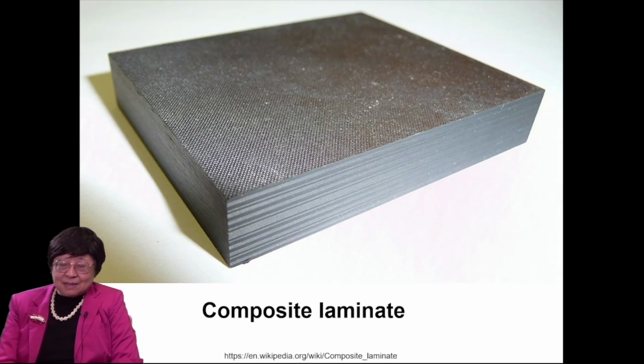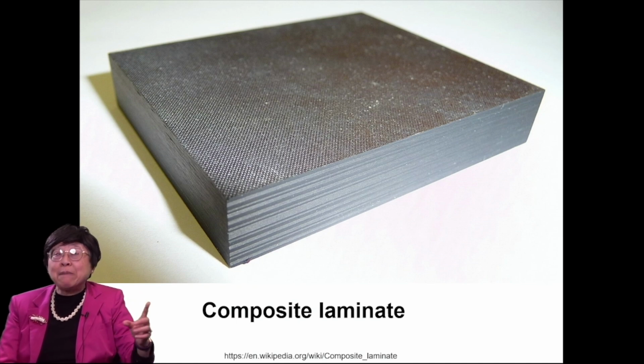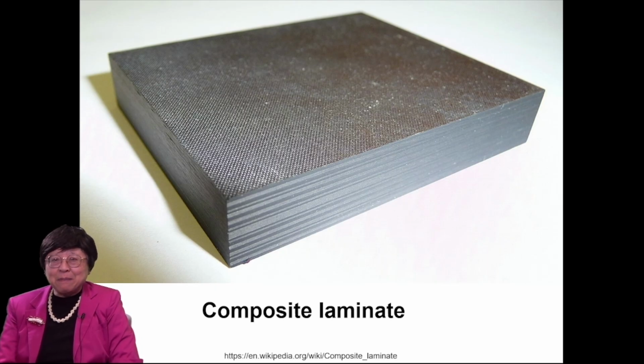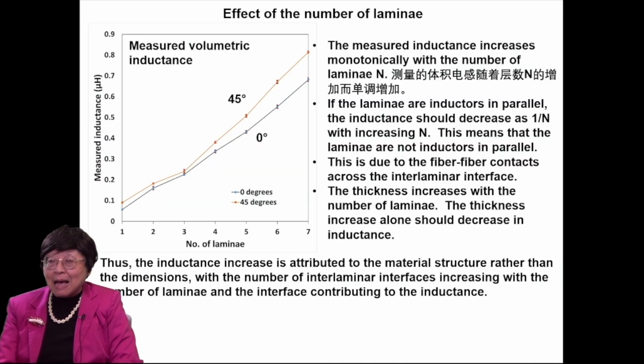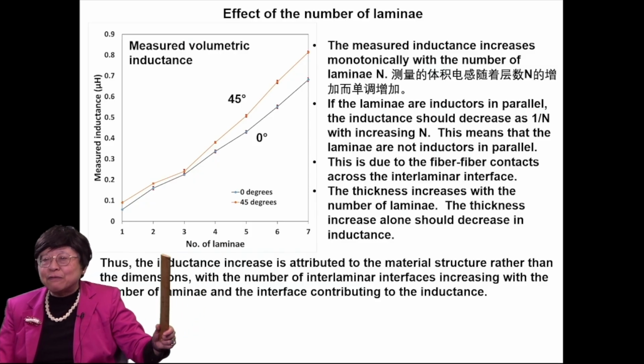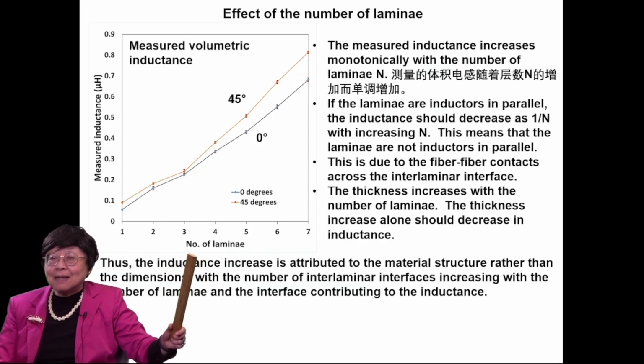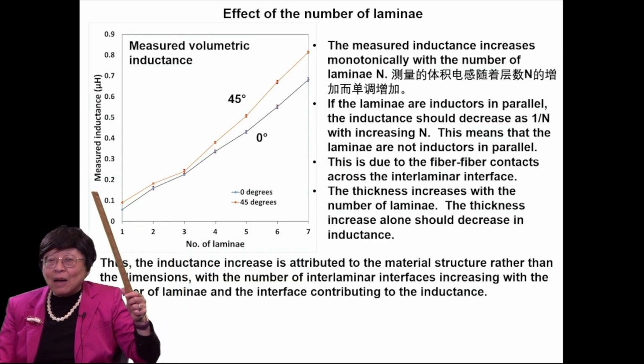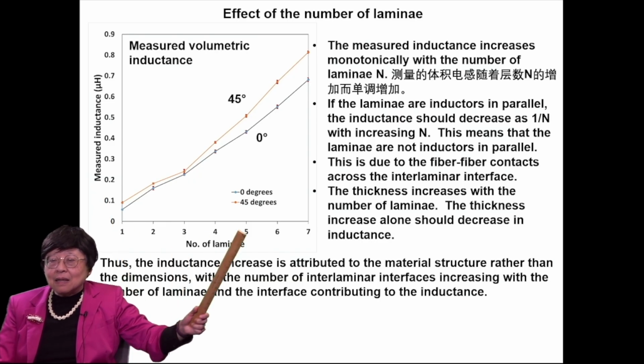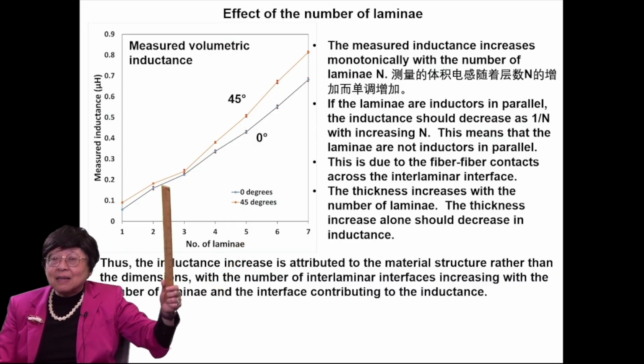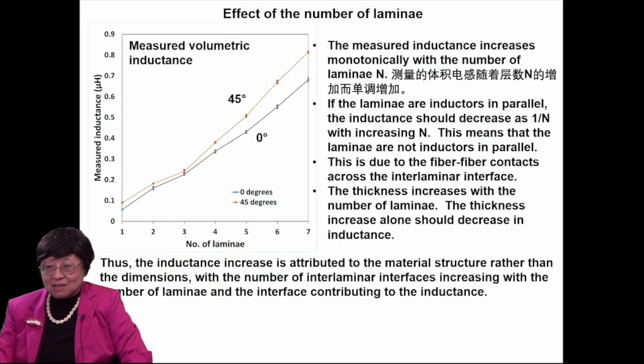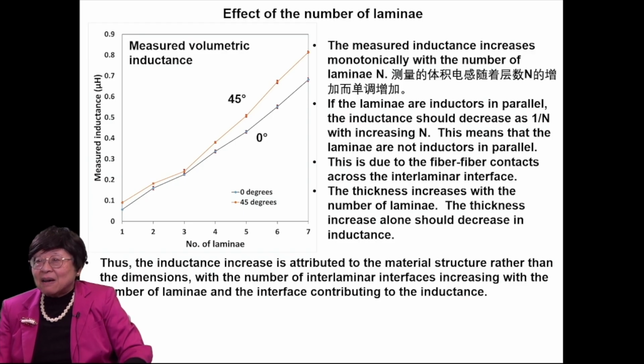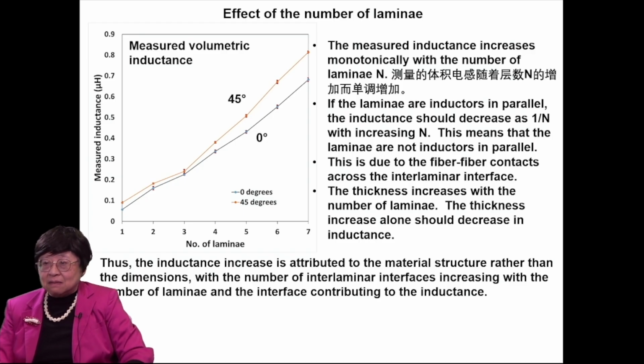Now, composite laminates, that's in practice very important. What I showed you is just one lamina, okay? But in practice, it's not one lamina, but many laminae making a laminate. So let's look at the effect of the number of laminae in the laminate, how that affects the inductance. The more the number of laminae, the larger is the inductance. Now, if the laminae are inductors in parallel, the inductance should decrease as 1 over n, where n is the number of laminae.